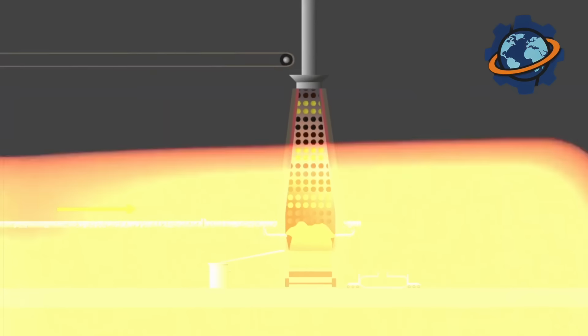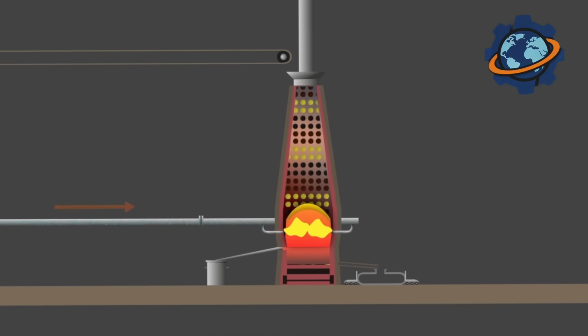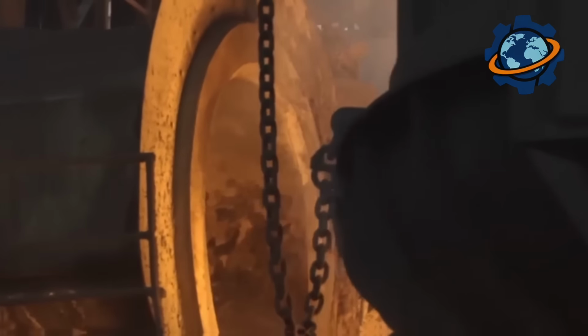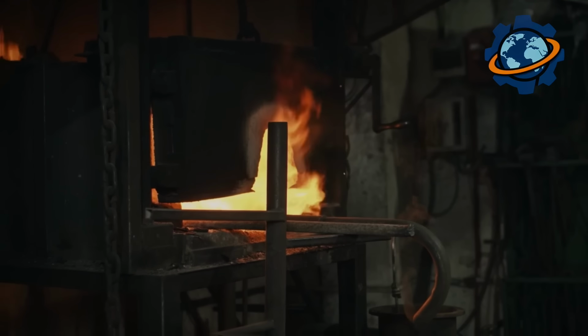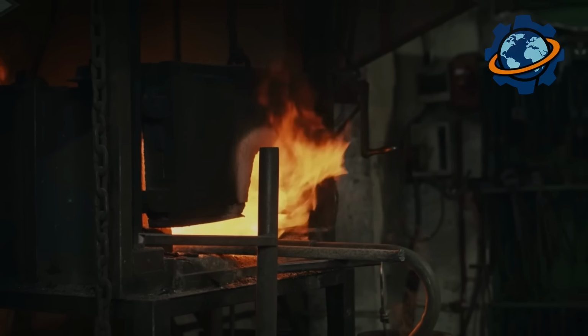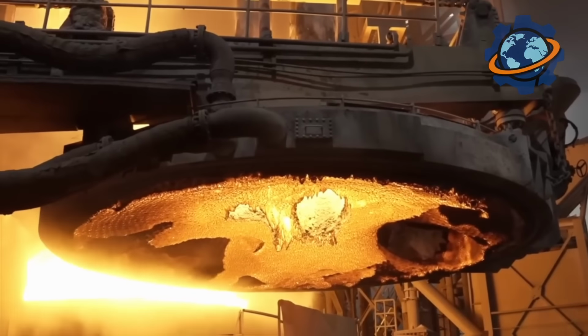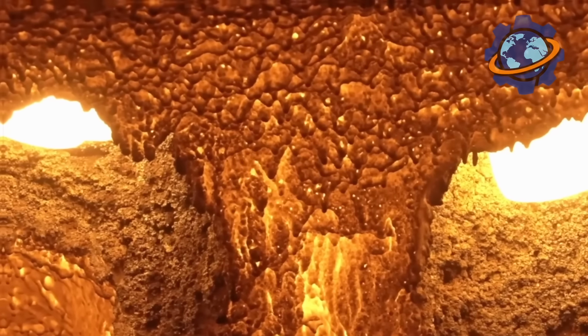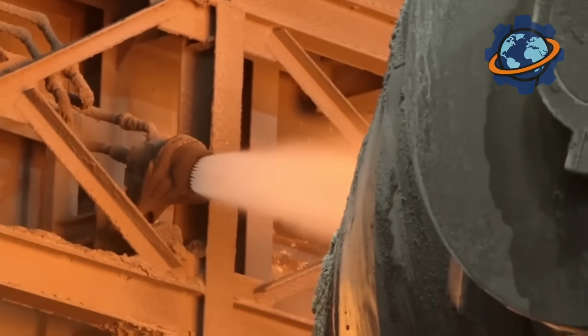Flame tongues several feet high shoot from the converter mouth. Sparks and molten drops fly everywhere. The blowing process takes 20 minutes. In this time, 350 tons of pig iron become steel. Carbon burns down to 1% or less. The converter tilts, steel pours into a ladle.